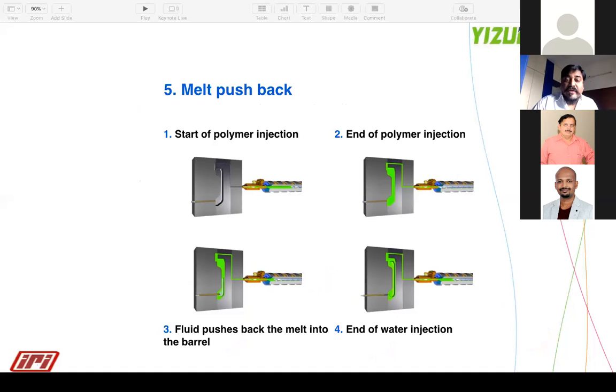And before, we had purge out technology where you have to take out the extra material and grind it or reuse it. But the new technology is melt pushback. You can see the slide. First, the polymer is injected. Once injected, the nozzle is putting the water inside, so the material goes back into the cylinder. So we don't waste the material; it is going back into the cylinder. So the hollow is created by pressing the hot water, and once the injection is finished, during the cooling time, we can switch over to the cold water. The water circulating inside the part, so that the cooling time is also very low. So that's how you create a hollow part.